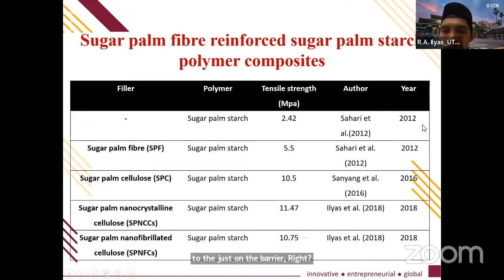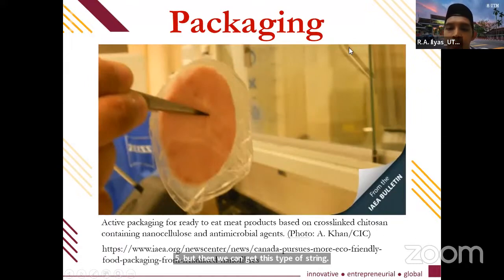The research was done in 2012. When we reinforce with raw sugar palm fiber, the mechanical strength of the starch increases up to 5.5. Then with the cellulose, 10.5. Then with sugar palm nanocrystalline cellulose, up to 11.47. And sugar palm nanofibrillated cellulose reinforced with the sugar palm starch increases up to 10.75. However, if you see this one, it takes 30% of the natural fiber cellulose to get this tensile strength. However, when we include only 0.5%, we can get this type of strength. So this research can really contribute to packaging applications.